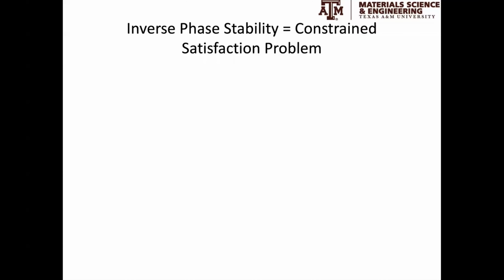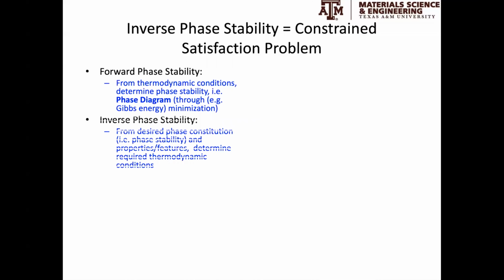Inverse phase stability can be understood in contrast with forward phase stability. In our group, we consider forward phase stability as the problem in which we use thermodynamic conditions to determine the phase stability, or phase diagram, of a particular alloy. This phase diagram is predicted by minimization of the Gibbs energy.